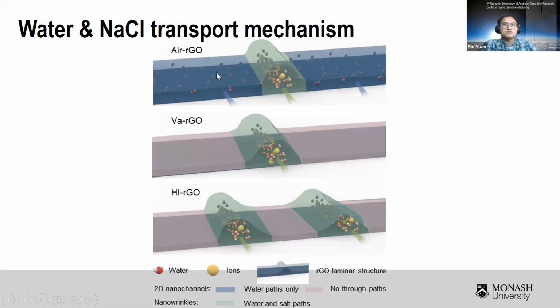There are two types of channels in RGOMs, the 2D nanochannel and the nanowrinkles. When the interspacing is too small, like that in vacuum RGO and HI RGO, water and salts can only go through the nanowrinkles without any selectivity. So these membranes will show smaller water flux and lower sodium chloride rejection.